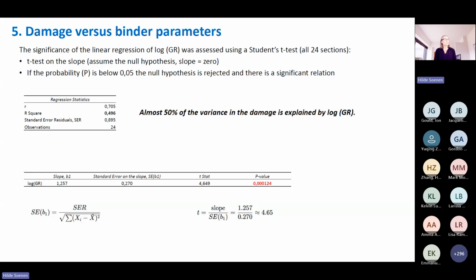What else did we do? Since we had so many sections, we were able to do a significance analysis. So assuming a null hypothesis that there is no relation, you check what is the probability of having this null hypothesis. And the lower this probability is, the more significant your correlation is. So in this case, it's very low, so we can reject the null hypothesis and say that there is a real effect here. So almost 50% of the variance in damage is explained by the Glover-Rowe.